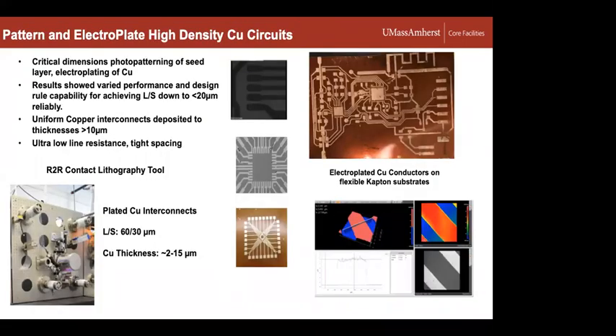So finally, in terms of the patterning approach, we did some work both with photolith patterning and electroplating, and this is more for high density copper circuits. And so typically on this, we're using Kapton substrates. We can use PET, there's no reason not to. It's a low temperature process. Basically, we expose a photoresist pattern with a photomask. We develop that. And in this case, we had a copper seed layer already coated on the substrate. For the exposed areas, we go into an electroplating bath, and then that will basically plate up or electrodeposit films as a function of time and current and so on.